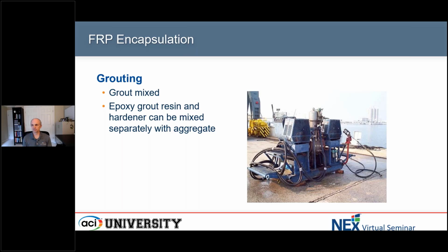So here's just a piece of pumping equipment that's being used to mix and pump an epoxy grout. This pump has two separate hoppers. One hopper is for the resin with aggregate or sand, one's with hardener and sand. And again, those are mixed separately, pumped separately, and then mixed right before they enter the annular space between the jacket and the structure.